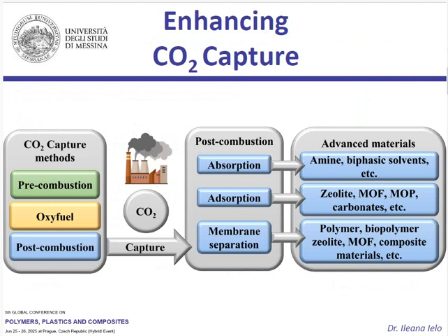Classic approaches like absorption and membrane separation can be significantly improved by advancement in their nanocomposite constituents. Starting with absorption, a key improvement involves the use of biphasic solvents, which are amine alcohol mixtures, and ionic liquids like imidazolium salts, which can convert into two phases, facilitating chemical absorption and potentially simplifying the regeneration process for reuse. The anionic part of ionic liquids promotes CO2 absorption, while the cation affects solubility.